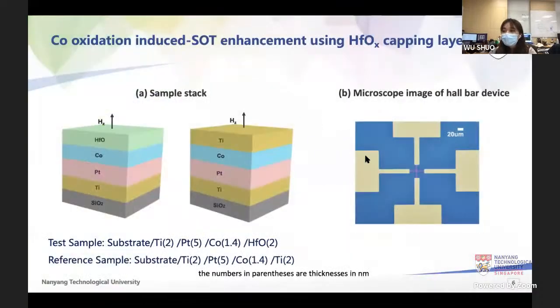One part is spin-orbit torque enhancement. In this work, we investigated a sample of a Pt/Co/HfO stack as our test sample, and a Pt/Co/Ti stack was also prepared as the reference sample for comparison. This is a schematic configuration, and this figure shows the symmetric Hall bar with 10 micron width and 100 micron length, fabricated with electron beam lithography and argon ion milling. These yellow areas are the contact pads.